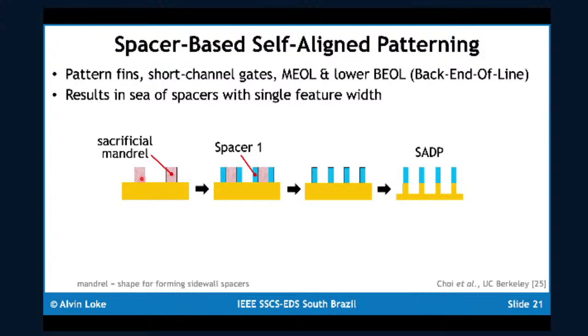You start by patterning with a single exposure a sacrificial mandrel, and use this mandrel to grow or deposit and etch spacers on the sidewall. You now have 2 spacers for every mandrel, which means that after you remove the mandrel, you're left behind with twice as many spacers at half the pitch of your original mandrel. You can then use this pattern as a hard mask to pattern your features underneath.